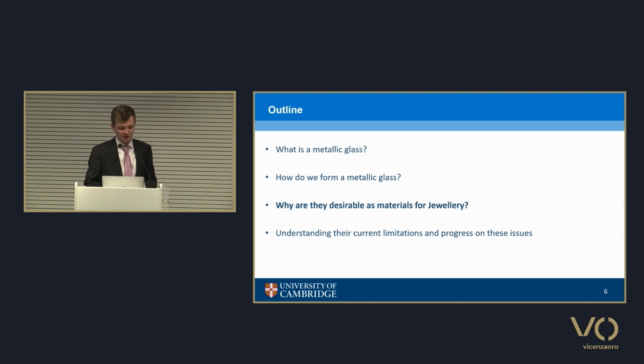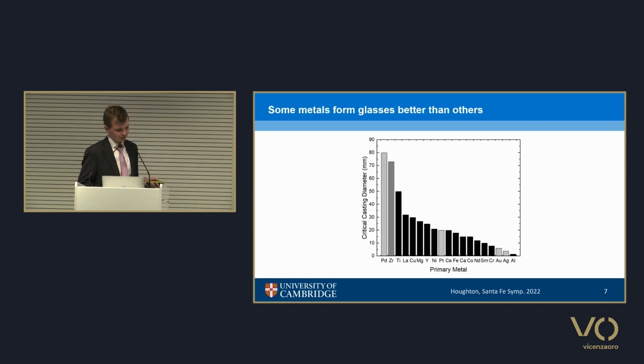minimal heat losses involved. So since the advent of platinum and gold-based glasses, which was by Boonrat Lohwongwatana, and as Ulrich explained, those glasses have sufficient hallmarking standards for the jewelry trade. So as you can see, there is a wide variety in glass forming ability. As Ulrich was saying, we have this critical casting diameter, which scales with cooling rates. And we call any glass a bulk metallic glass if it can be cast in sections thicker than 1 millimeter.